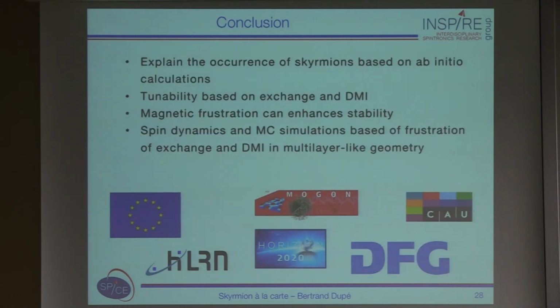And so this brings me to my conclusion. Overall, we can explain the occurrence of skyrmions based on density functional theory. We can tune their properties based on exchange and DMI, especially with the frustration. The magnetic frustration, especially from the exchange interaction, can actually enhance stability. It's not only something which destroys the skyrmions. We can do spin dynamics with Monte Carlo based on these DFT parameters, with long-range exchange interaction in a multi-layer-like geometry also.